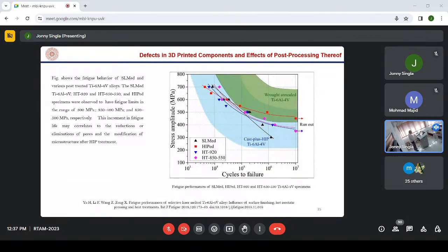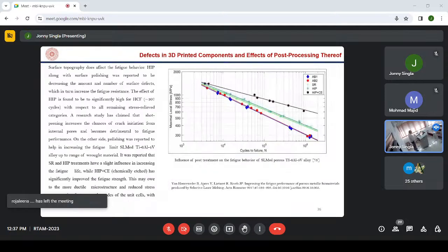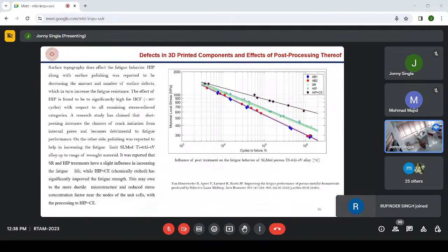This is again the same 3D thing. Again, in this study, it has been found that if you carry out HIP and supplement it with chemical etching, HIP followed by chemical etching, then it gives even better results as compared to HIP treatment alone. Right? So this way, HIP plus chemical etching can be used for improvement in the fatigue properties or the dynamic properties.